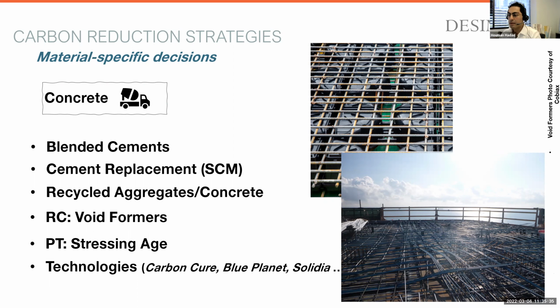However, again, you need to be a little bit careful because when you're using recycled aggregates, the quality control of the material is not the same as if you were using brand new crushed stone, right? So it can affect some stuff, including water absorption in the concrete, and then eventually it shows itself in shrinkage. And if you are pouring a flat slab in Florida in summer, shrinkage is not your friend. So you don't want to play with something that exacerbates that shrinkage problem that you had. So it can be done. I think it has to be controlled to a certain amount based on what I know today.